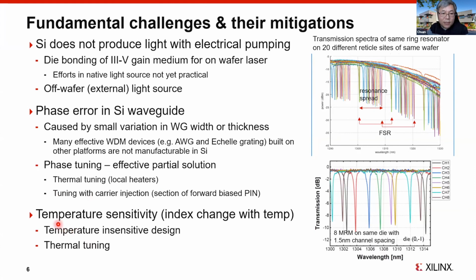The third challenge is temperature sensitivity. This actually works both ways. On the negative side, when you make, for example, a silicon resonator, it hits one resonance frequency at, say, room temperature. When the temperature changes, that resonance frequency or wavelength will change with temperature. Of course, the way to counter that is, again, to use thermal tuning. There are also ways to design devices that are athermal. You basically introduce some other material with a negative temperature coefficient to counter the index change of silicon with temperature.